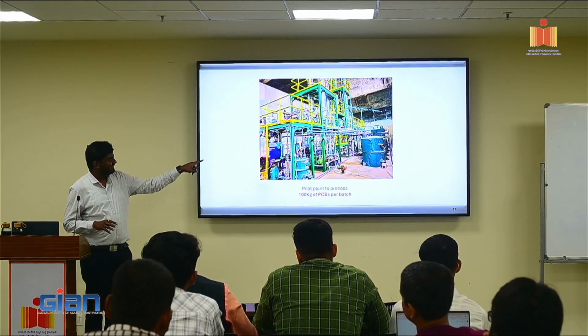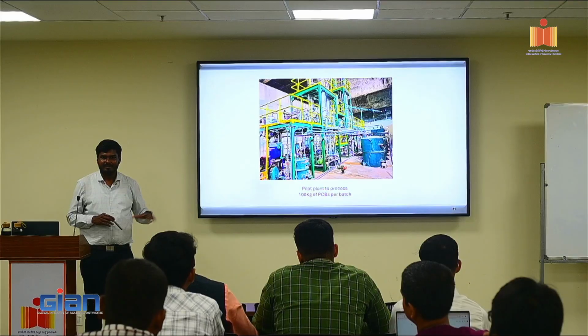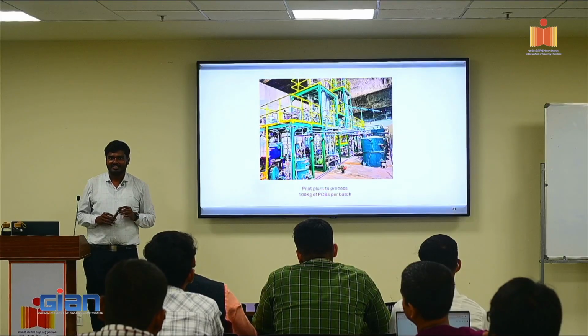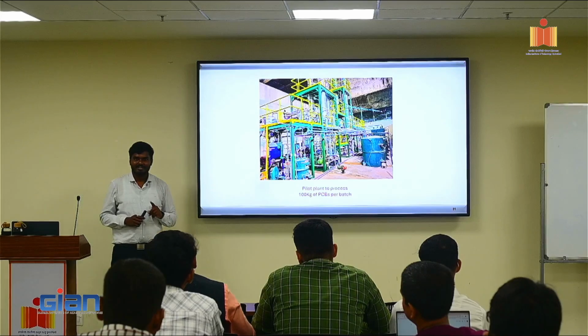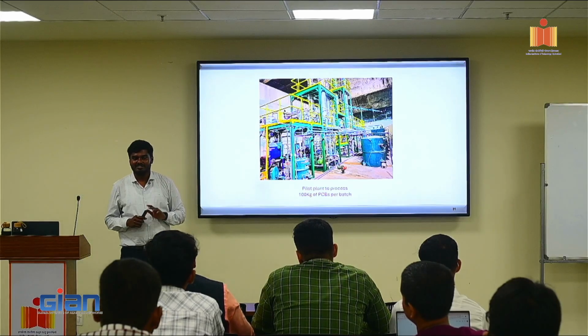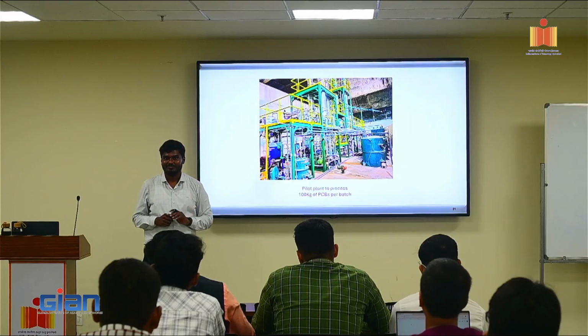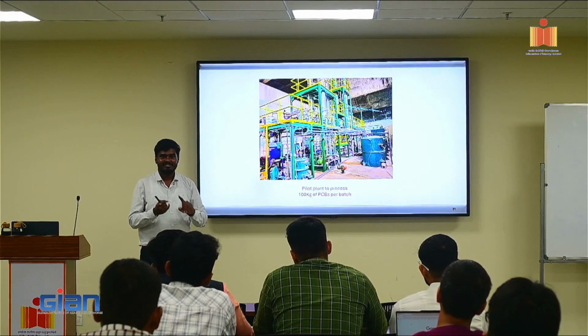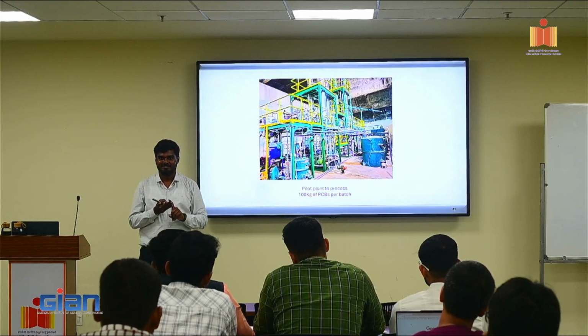And the third-party vendors helped us set up this pilot plant, and this plant can process 100 kgs of PCB per batch, and per day we can process around 3 batches. It's around 300 kgs per day that we can process. This was successful and we were able to recover lead, tin and copper.